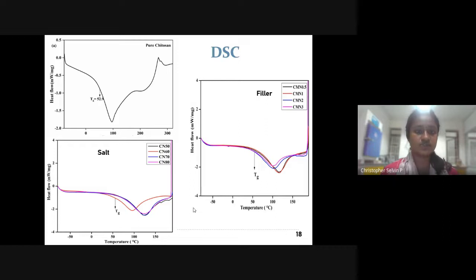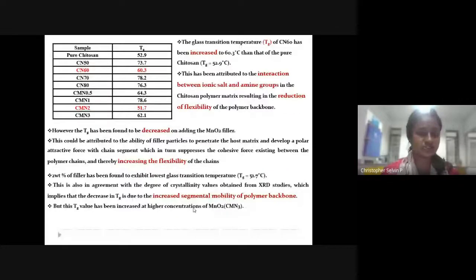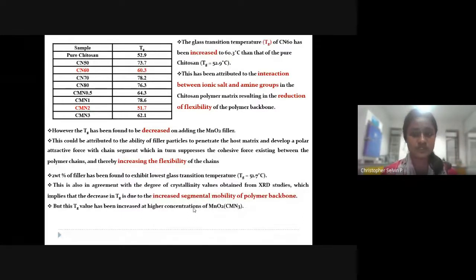The first one shows the DSC of the pure chitosan, and the Tg values, that is the glass transition values, have been tabulated here. As you can see here, the glass transition temperature is found to be higher on adding the salt than that of pure chitosan. This is due to the interaction between the ionic salt and the amine groups in the chitosan polymer, which affects the flexibility of the polymer chain. However, this value is found to be decreased on adding the filler.